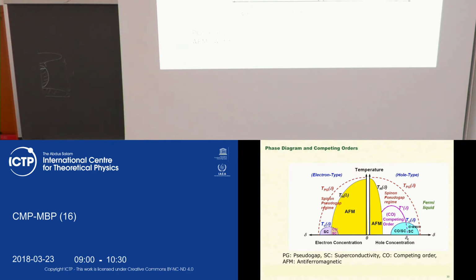This is hole-based superconductors, typical representatives. This is yttrium barium copper oxide and lanthanum copper oxide, or a system with mercury, with thallium. So what you see, this is doping versus temperature. Zero doping means half filled material. So at half filling you have an insulator and antiferromagnet. So you dope the system and you destroy the antiferromagnet. Then you dope it further and superconductivity starts to develop, and superconductivity forms the so-called superconducting dome. The dome means that there is a doping at which superconductivity reaches its maximum Tc. Moreover, in this cartoon it's not that clear, but in principle this dome is not very symmetric.